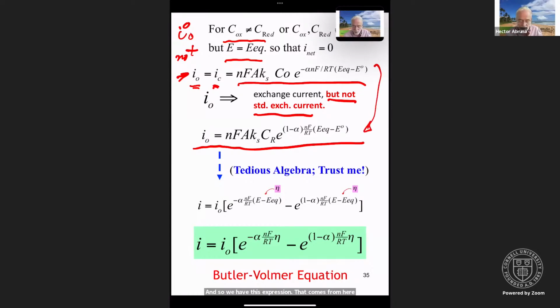There's more tedious algebra, and on this one, trust me, we end up with an expression down here. This is I equals I0 times e to the minus alpha nF over RT, E minus E equilibrium, minus e to the 1 minus alpha nF over RT, E minus E equilibrium. Remember that this is our definition of an overpotential. And so from here, we can come up to this expression, I equals I0, the exchange current, times e to the minus alpha nF over RT eta, minus e to the 1 minus alpha nF over RT eta.